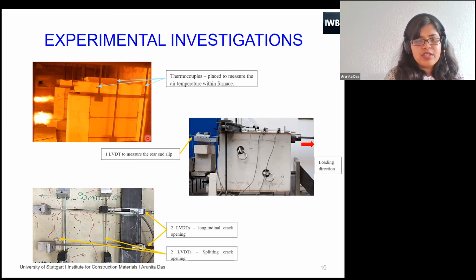As I have mentioned earlier, all the specimens were first exposed to the fire, and then the furnace was closed, and they were allowed to cool down naturally for around 24 hours. Then the furnace was opened the next day, and the specimens were taken out, and then the pull-out tests were carried out to check the residual bond capacity of the rebar. This is a specimen which was already inside the furnace.